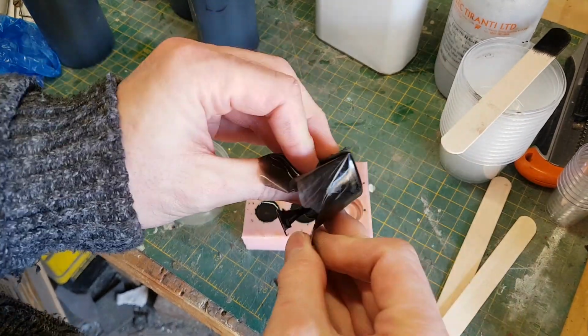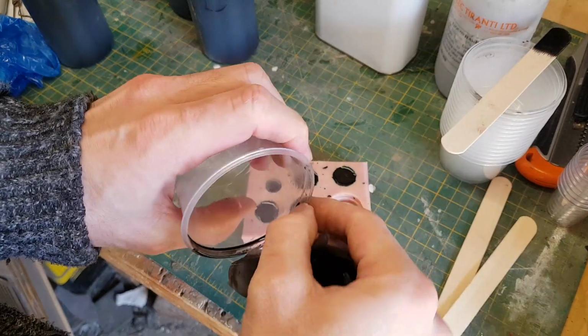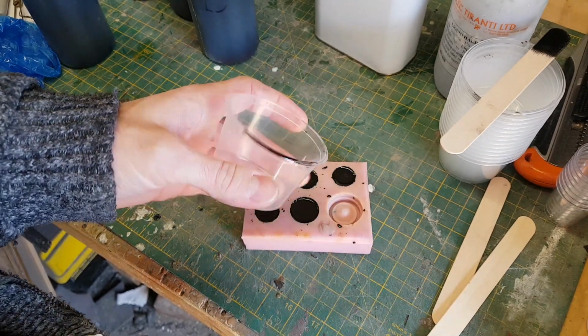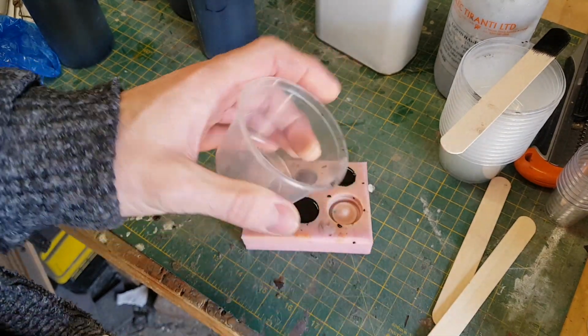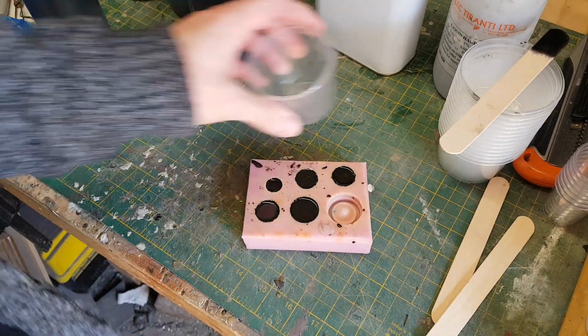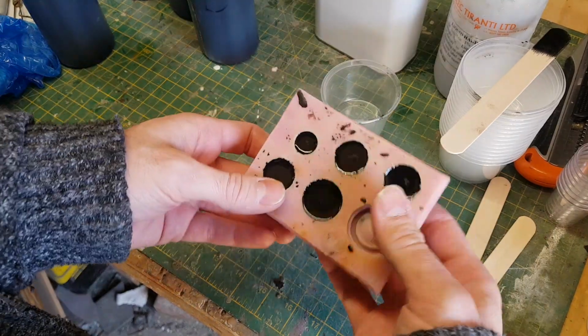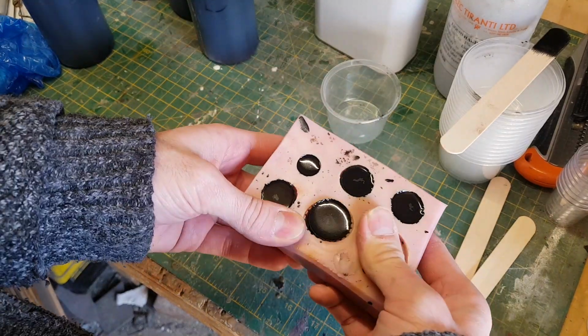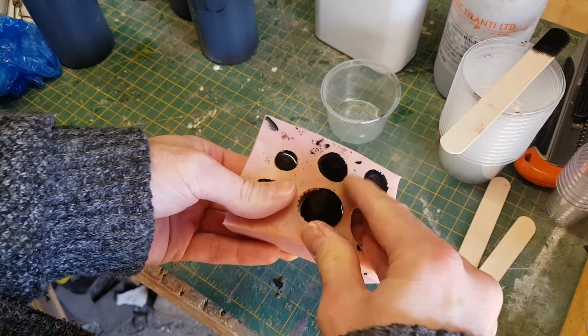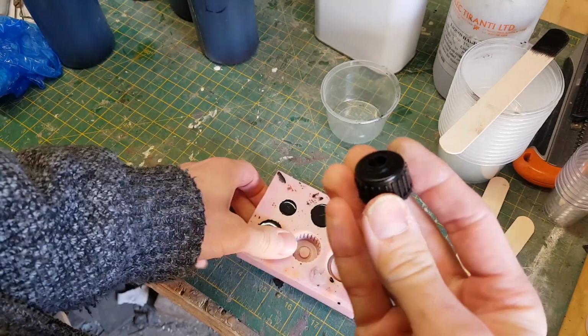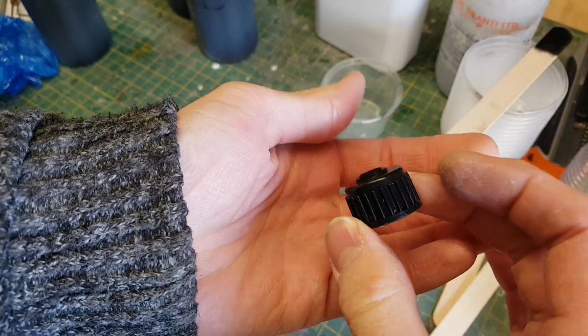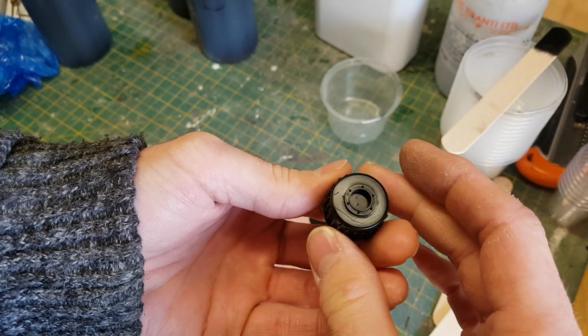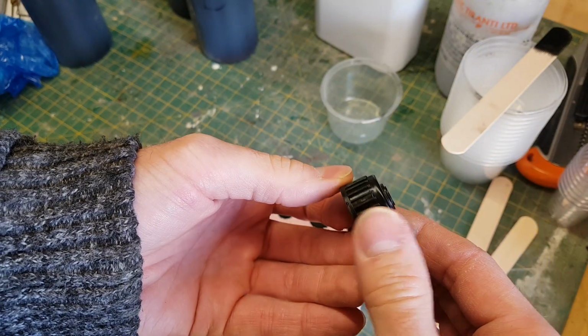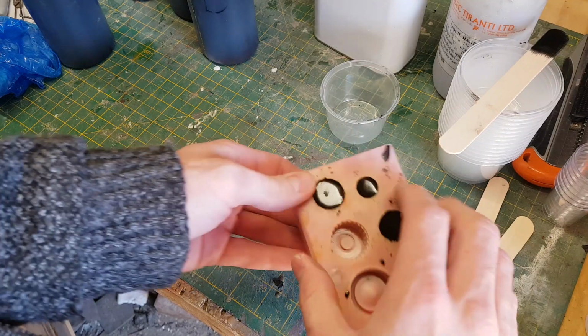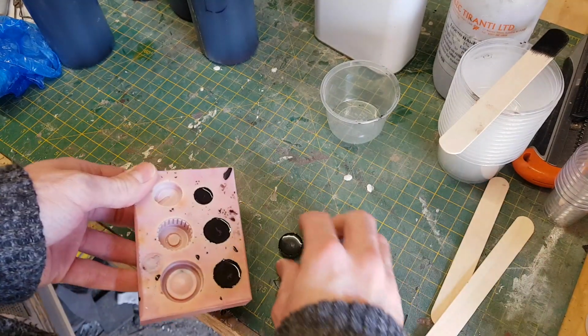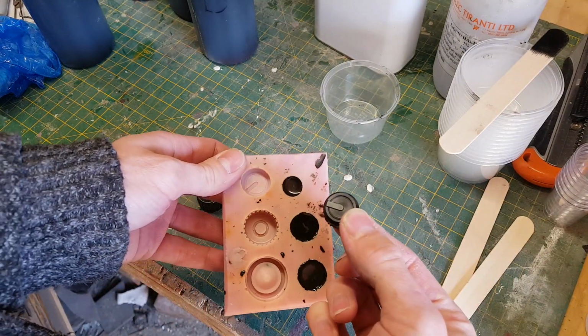You don't notice it so much for small pieces, but the way polyurethane resin works when it's setting is it gets quite hot, and the hotter it gets, the quicker it cures. So you will find for larger pieces that the resin can actually get really, really hot. The same is true of polyester resin too. They both have an exothermic reaction, which means they give off heat as they cure. And for larger pieces, certainly, they can sometimes be a little bit too hot to actually comfortably rest your hand. So if you are doing larger pieces, don't be alarmed if these things start getting really, really hot. That's how they work.